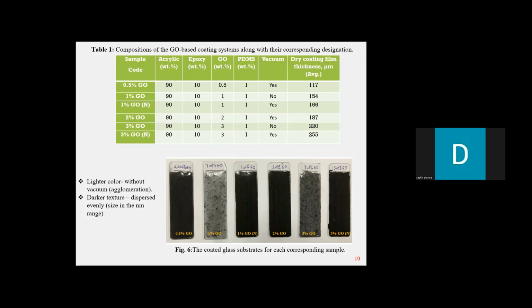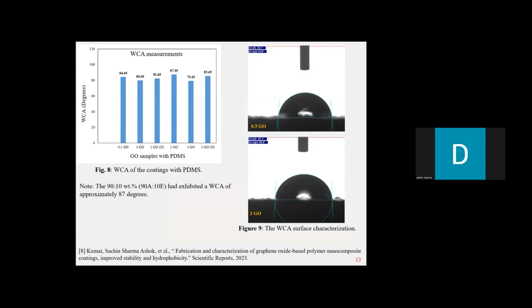So it's basically 10:1. So if you are using 10 weight percentage of epoxy, we use 1 weight percentage of IPDA. That is to ensure that the cross-linking has occurred between both the resins. So for the results and discussion, let's look at the water contact angle, and let's look at figure 8.